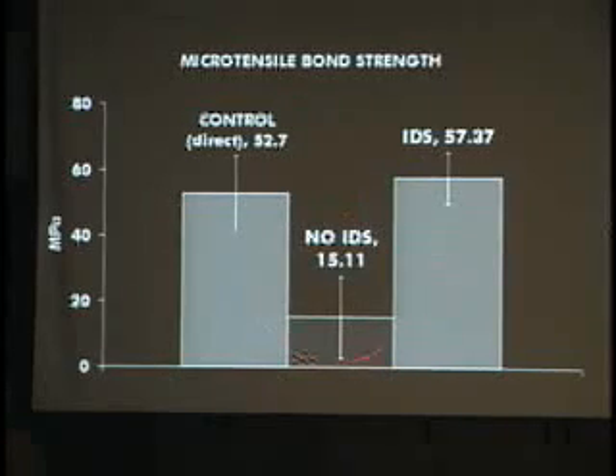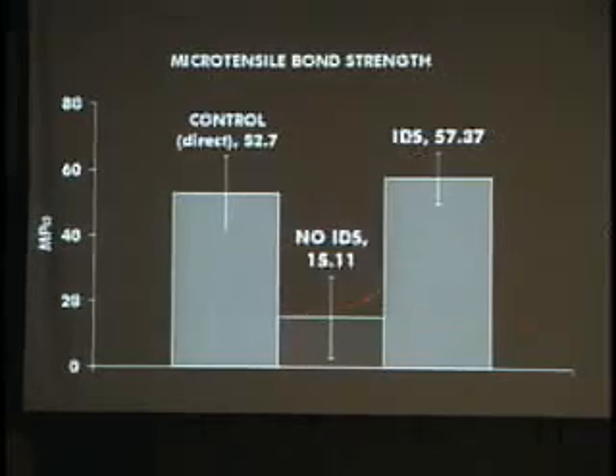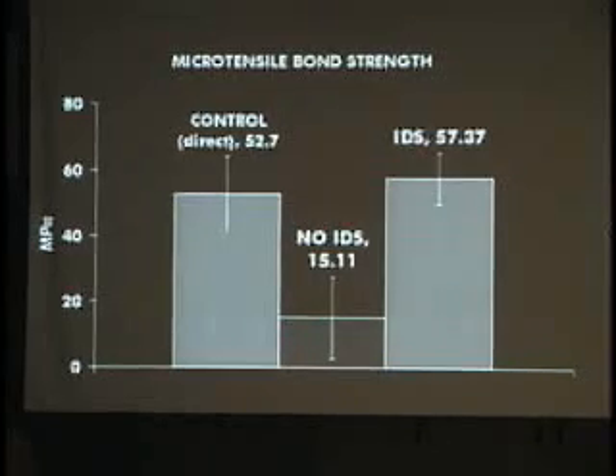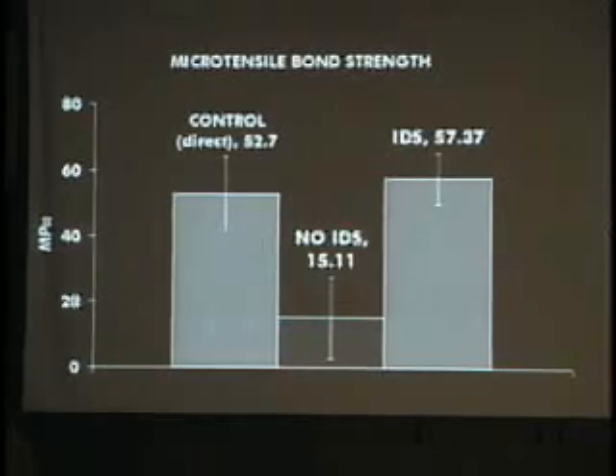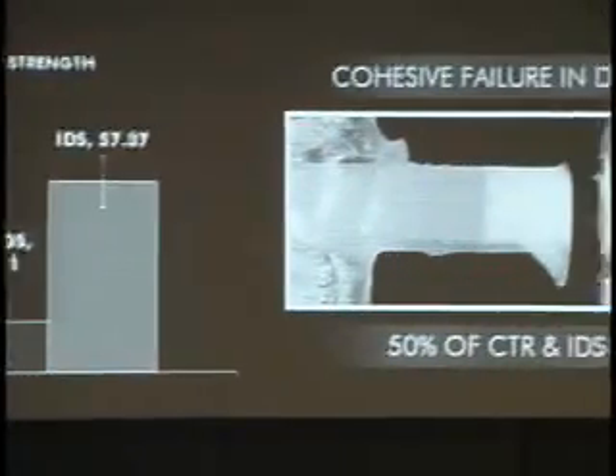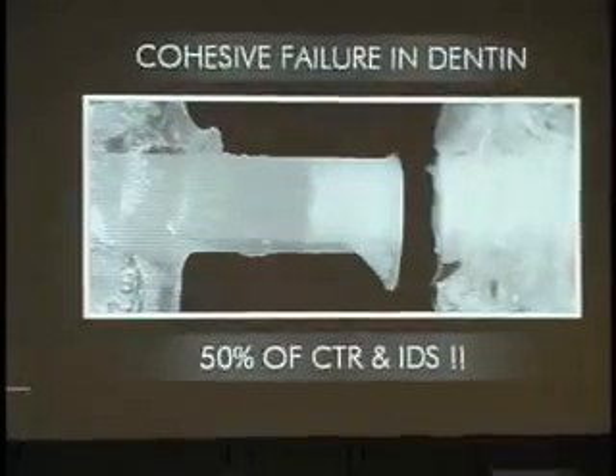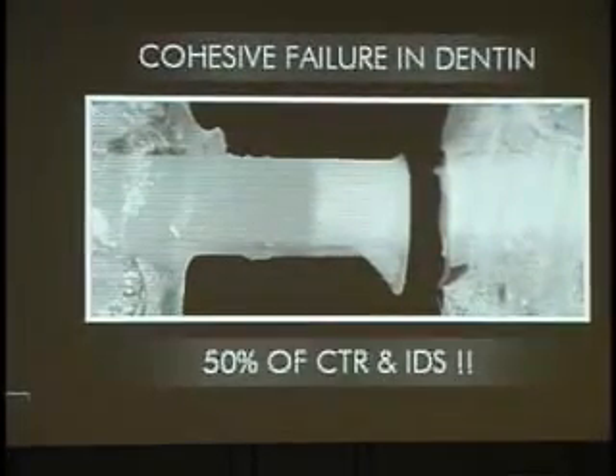If you don't seal dentin immediately, because the adhesive cannot be cured, because dentin is contaminated, you lose completely the bond, and 100% of these samples failed adhesively, as you can see here. While we had most of the time cohesive failure in dentin when we sealed dentin straight away, and we used this existing adhesive layer as a bonding layer during the final placement of the restoration, so cohesive failure in dentin.